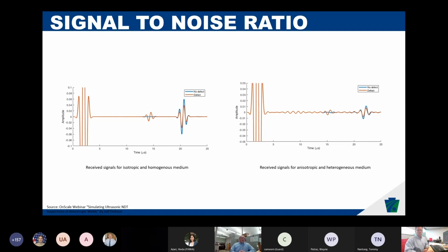So, like I said, it's more significant on the shear wave process because the refracted angle involves Snell's law. The velocity is a function of Snell's law, so it basically will throw off your ray tracing, or in some cases it causes a complete loss of energy at some of those higher angles. It causes mode conversion, so you actually have the ability to miss discontinuities if you don't consider this property on some of these steels.